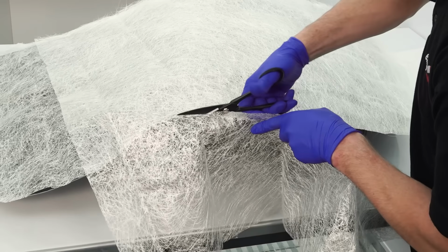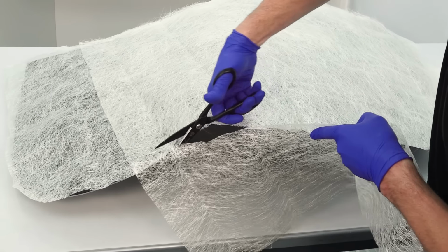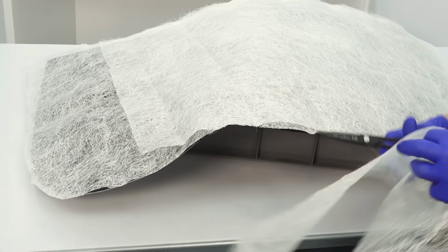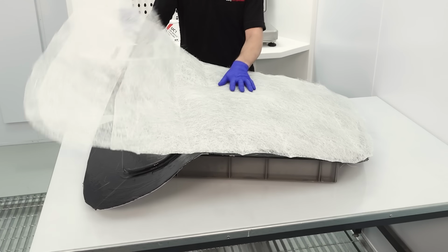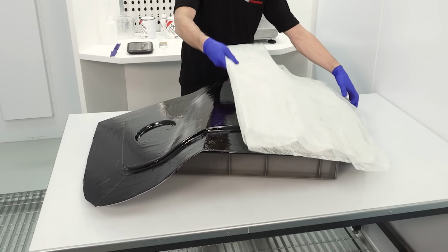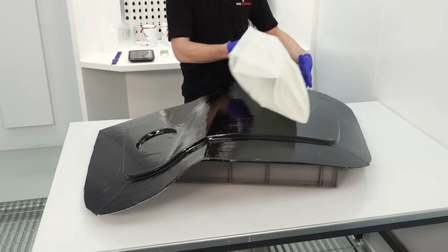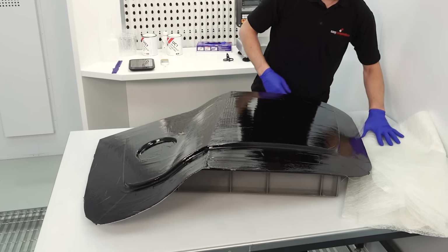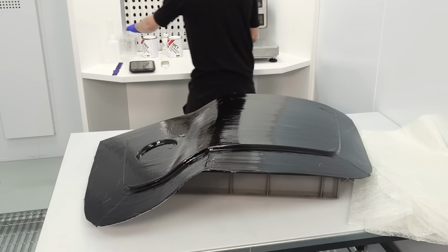When doing multiple pieces, you should allow a small overlap to ensure that you get a full coverage of reinforcement on your mould. When doing this, it's often best to tear the edge of the matting, as this is going to give you a feathered edge that's going to blend nicely with the adjoining pieces.